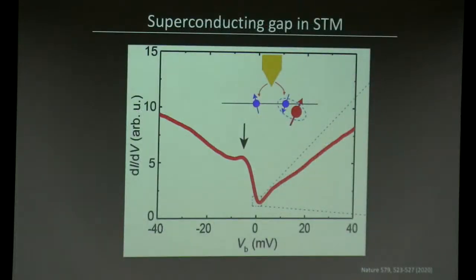Okay, so now knowing that this is a triplet superconductor, let's do STM and look at the superconducting phase of the system. Remember that this Kondo physics is happening at high temperatures, so the energy scale of this stuff is about 10 millivolts. Superconductivity is happening at 1.6 Kelvin in the sample I'm going to show you, and that energy scale is less than 1 millivolt. So in order to look for superconductivity, we have to look right here.